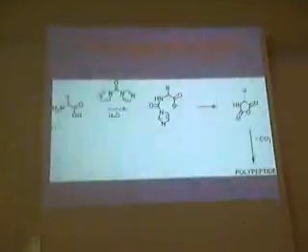So it seems that when the pleated sheets are formed, the R inhibits or impedes the growth of the S chains, whereas in the case of the racemic it is just the reverse, and on this basis we concluded that we are dealing with a racemic system.